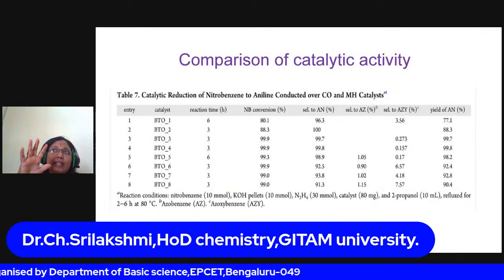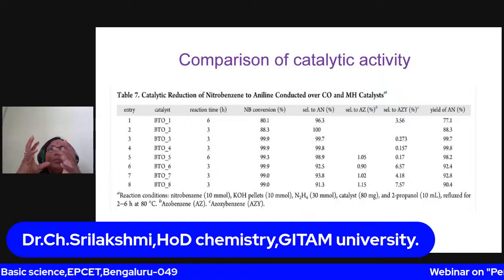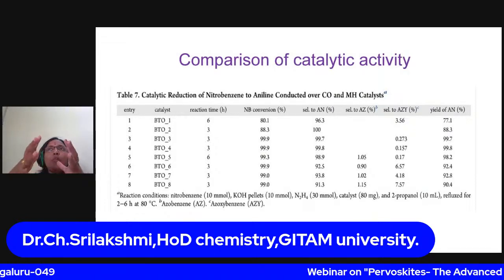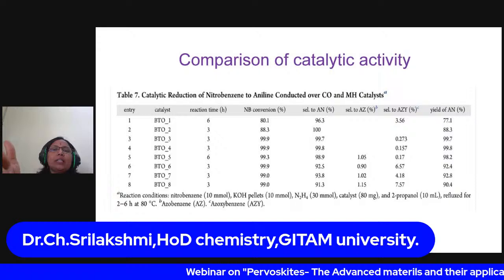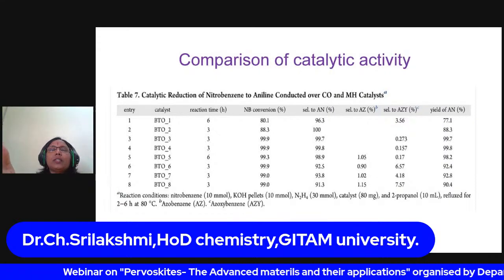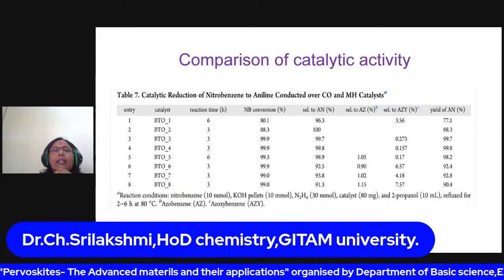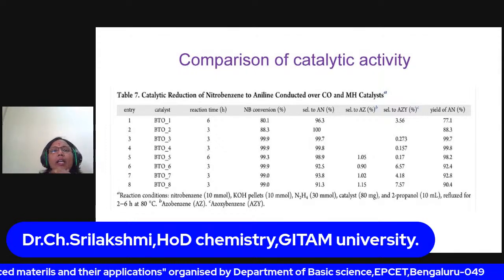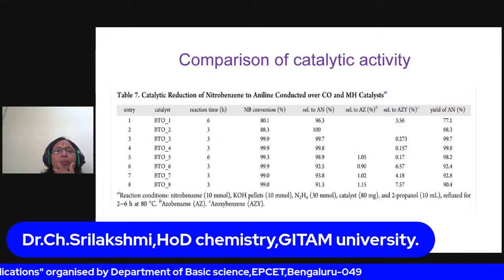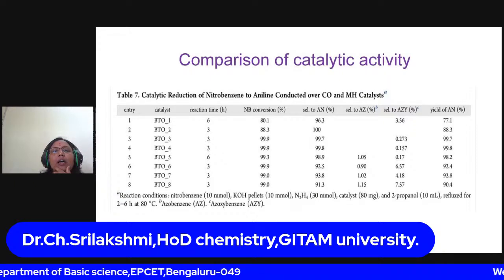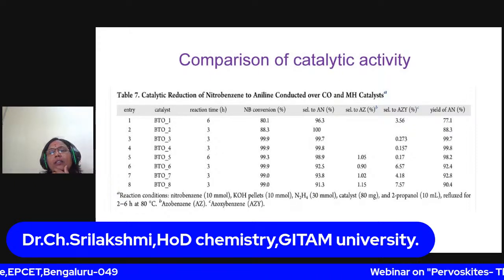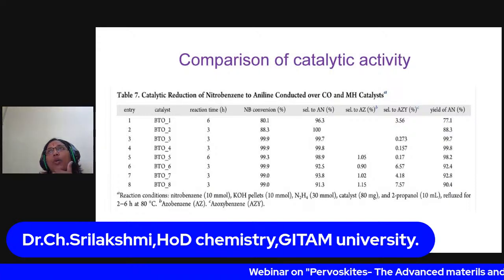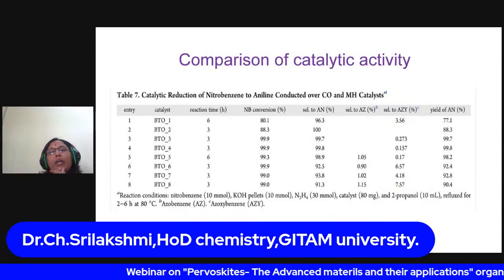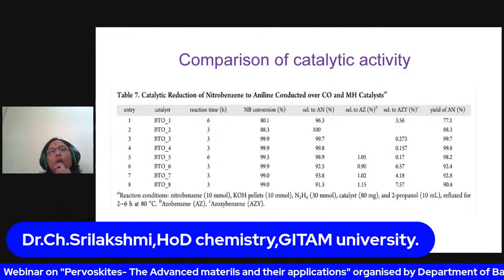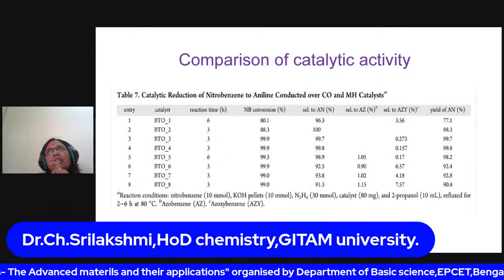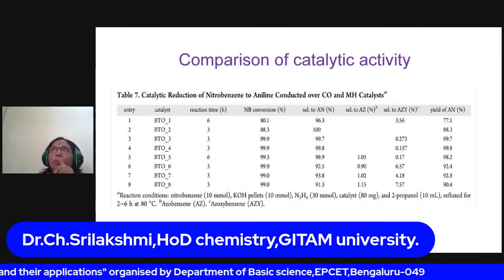So these results indicate the role of the promoter chromium. It is obvious in the conventionally synthesized catalyst, because with an increase in chromium content, conversion increased. But here I don't see any improvement: conversion remains constant and selectivity goes down because it is blocking the active sites. The only role of chromium in microwave synthesis is that it facilitates the reaction in a short time.